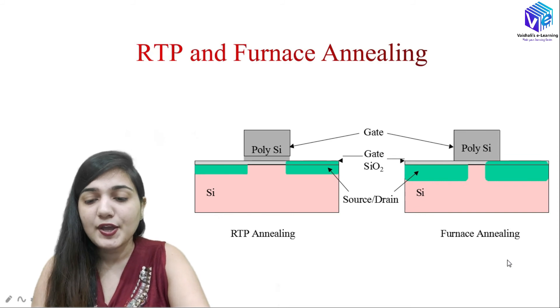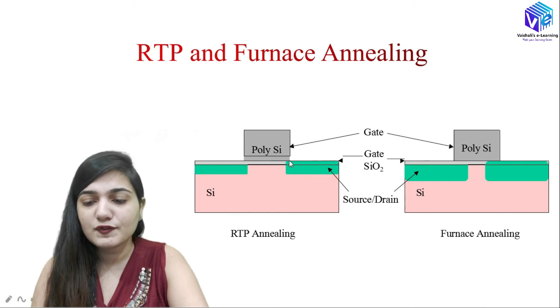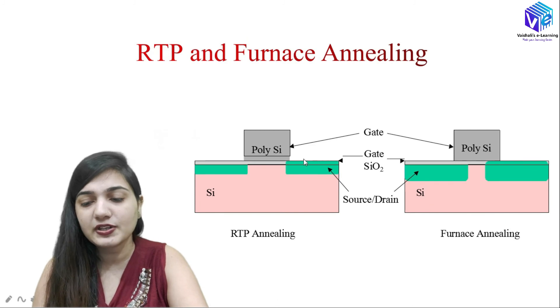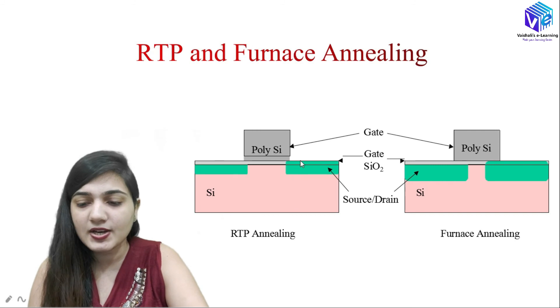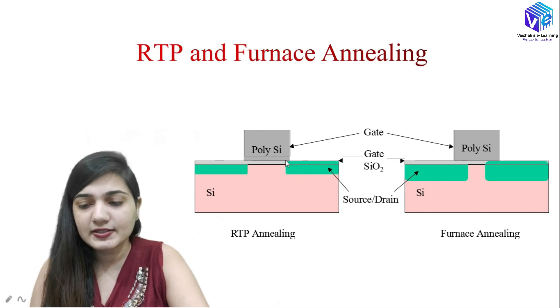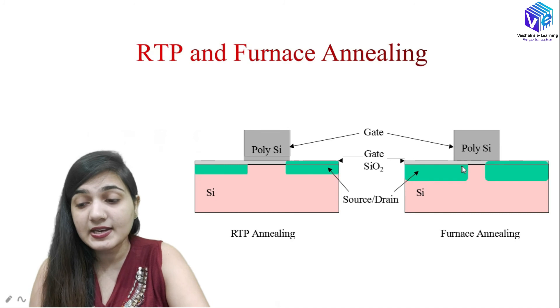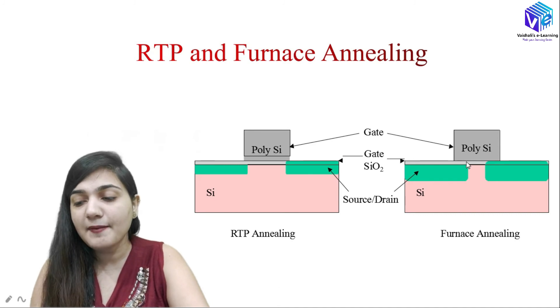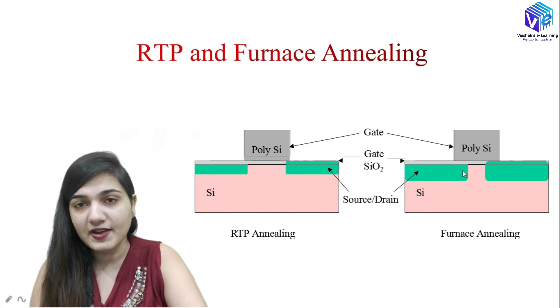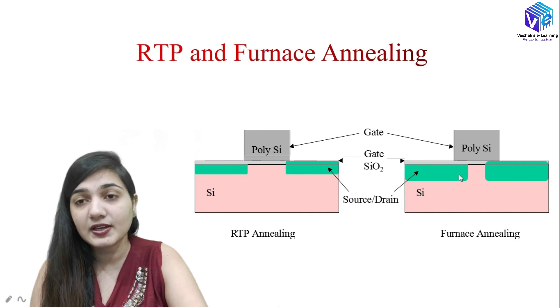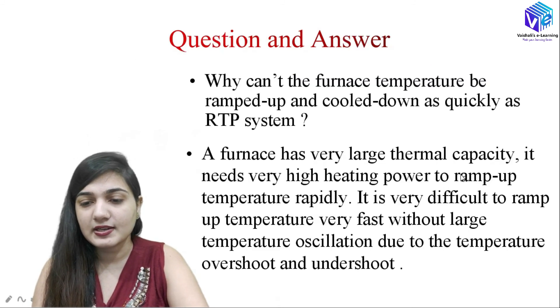You can see the comparison between RTP and furnace annealing. In RTP annealing, diffusion is not predominant, so I have the perfect doped region that I want — I don't want to degrade this structure after doing the ion implantation. In furnace annealing, supplying high heat causes the diffusion process to occur and the doped profile region will have a lateral effect — it will move in the lateral direction as well.